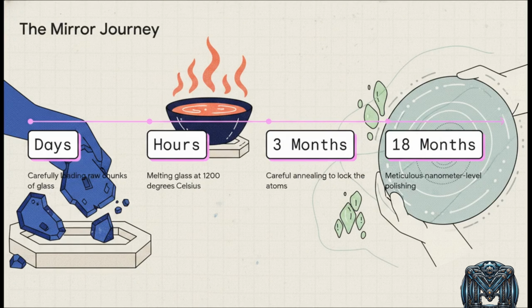When you zoom out and look at the whole timeline of the mirror's journey, the contrast is staggering. You spend a few days carefully loading raw chunks of glass into the mold. The actual melting phase at 1200 degrees, that only takes a matter of hours. But the finishing phases, the 3 months of delicate annealing to lock the atoms, and the 18 months of meticulous nanometer-level polishing take nearly 2 entire years. It is a literal marathon of precision engineering.